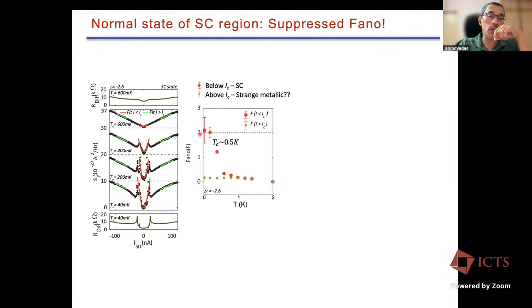And so most importantly, now the last part. I talked about the Fermi liquid regime, the Fano of 0.43, and the superconducting regime, the Fano factor of 2. Now we can do the Fano in the superconducting regime to make sure this is really Cooper pair transport. If you do it as a function of temperature, indeed the Fano factor decreases from 2 and becomes the same as below the critical current, above the critical current. So that makes sure that indeed above Tc the Fano factor reduces. So we basically confirm that really we look at the charge of the Cooper pair.